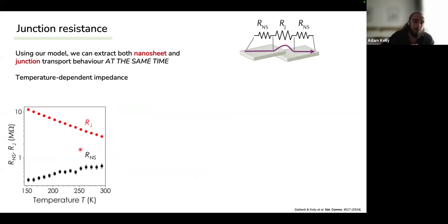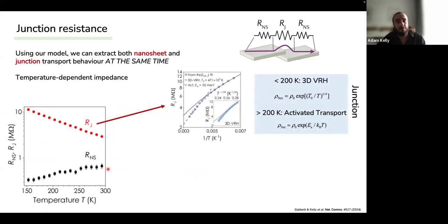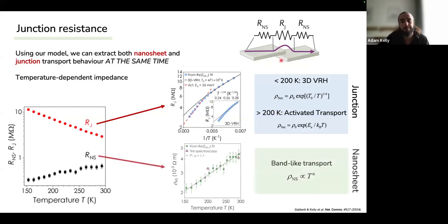So we do impedance at a range of different temperatures. This gives us junction resistance, which goes inversely with temperature, and the nanosheet resistance increases with it. So this means what we have here is behavior less than 200K, for example. We see 3D variable range hopping, and above 200K, we see activated transport, and that is behavior solely associated with the junction. When we look at the nanosheet itself, we see band-like transport. So this means that the nanosheet has more efficient transport properties than the junction.